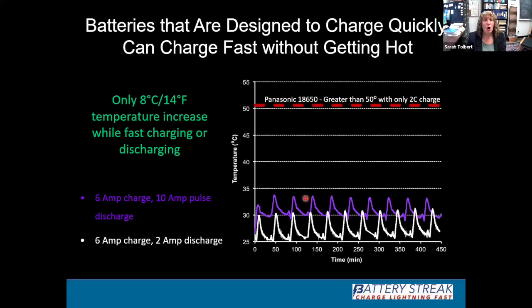And this is data on what happens when you try to charge a battery that is made to charge fast quickly, or a battery that is not made to charge fast quickly. And so this red line here is a conventional Panasonic 18650, a standard battery size. And if you try to charge it at 2C, that's a 30-minute charge. We're not talking the 3 minutes or the 30 seconds I was talking about, a half an hour charge. That battery heats up to above 50 degrees Celsius. So remember, body temperature is 37 degrees Celsius. So this is hot enough it would actually burn you if you touch it, okay? So half-hour charge, you get a burning hot battery.